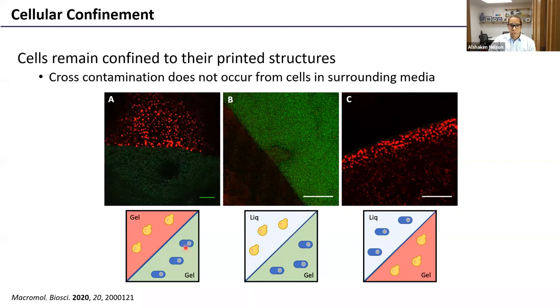For example, looking at the gel-gel interface between a red fluorescent yeast-containing gel and a green fluorescent E. coli-containing gel, this is after 7 days. Looking at the boundary between them, we see that the boundary is still pretty sharp. And we don't observe the infiltration of the yeast into the E. coli hydrogel, and we don't see the infiltration of the E. coli into the yeast hydrogel.